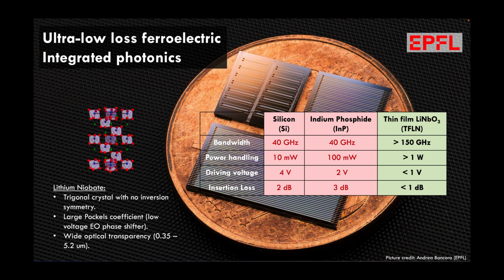vast bandwidth. The other aspect is that due to the large Pockels coefficient, the switching voltage for lithium niobate and also lithium tantalate can actually be sub-volt. So they can make a new class of optical modulators that is very compact, wafer-scale manufactured, and can challenge both silicon and indium phosphide in terms of performance.